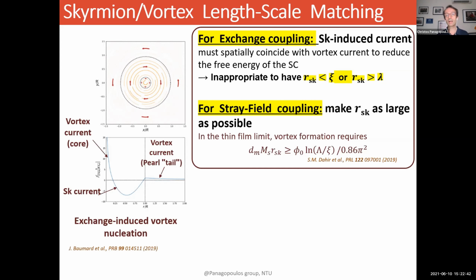For stray field coupling, you need to make the radius of your skyrmion as large as possible. And therefore, in the thin film limit, the vortices would form for as long as the product of the thickness of your superconductor with your magnet with the saturation magnetization and the size of the skyrmion is greater than the parameters shown here, and I will return to these numbers later.